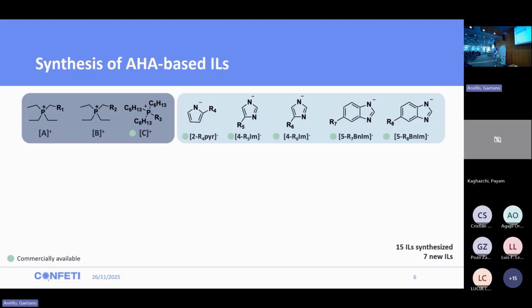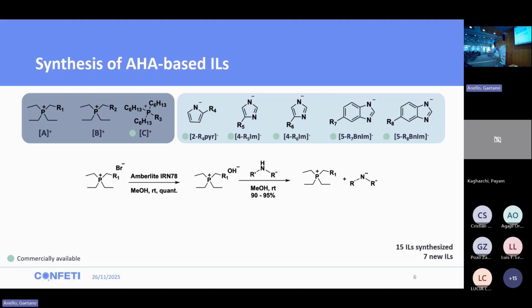So in this work, we developed the synthesis of ionic liquids, that is, the resulting combination of these 3 cations and these 5 anions, using a simple 2-step synthesis. We start from the phosphonium bromide that we convert into a phosphonium hydroxide using an ion exchange resin, and then using a neutralization reaction with the corresponding protonated form of the anion, we obtain the ionic liquid in really high yields.